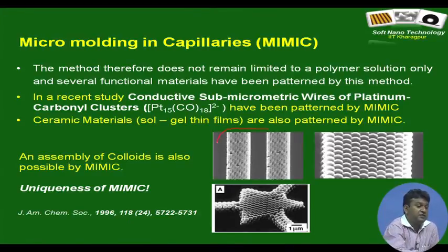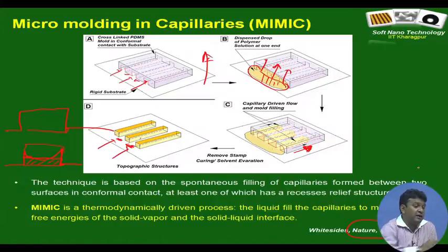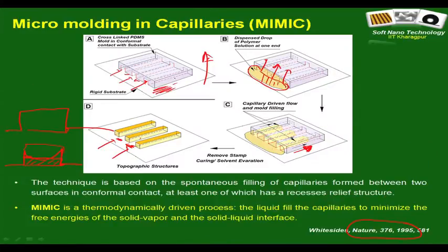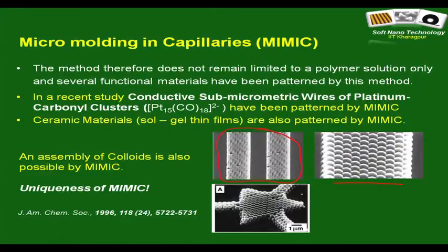Look at this SEM picture very carefully. You are seeing two stripes, but what is important is that they are not made of a polymer, they are made of a layer of colloids. That is the advantage, because MIMIC does not require a pre-existing film, right. It is a capillary driven flow, and instead of a polymer solution, if you dispense a colloidal suspension, the liquid will anyway flow due to capillarity, due to preferential wetting, and along with that the colloids will go on filling the molds. So, that is exactly what is shown here, and this capability cannot be replicated by any other soft lithography technique.